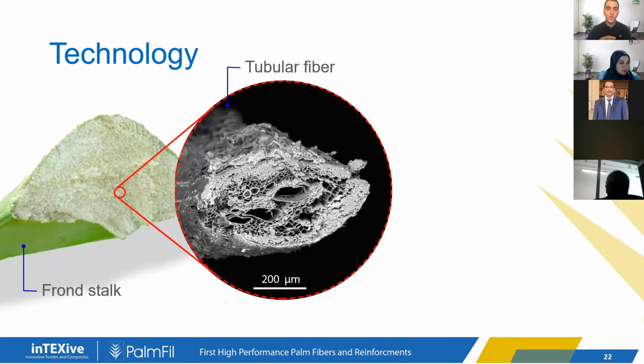And these tubular fibers are more like pipelines that are intended to transport the moisture and other nutrients to the different parts of the frond. But surrounding the wall of these tubular fibers, there are fine microfibrils. Unfortunately, those microfibrils and the tubular fibers are glued together, and glued with other tubular fibers inside the frond stalk, with a natural glue like the lignin and the hemicellulose. And as you can see here, there are still some traces of this natural glue.